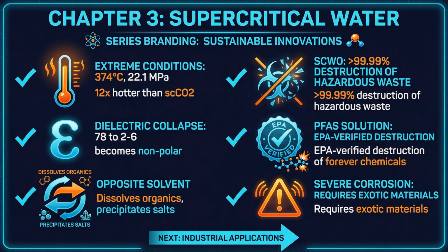Let's summarize the key points about supercritical water. Its critical parameters are extreme, 374 degrees Celsius and 22 megapascals, requiring specialized equipment and materials. The dielectric constant collapses from 78 to just 2 to 6, fundamentally changing water's character. This creates opposite solubility behavior, dissolving organics while precipitating salts. SCWO achieves greater than 99.99% destruction of hazardous organics in just seconds. For PFAS forever chemicals, SCWO is one of the only proven destruction technologies with EPA verification. However, severe corrosion requires exotic materials and careful engineering. In Chapter 4, we'll explore how these supercritical fluid technologies translate into commercial industrial applications.